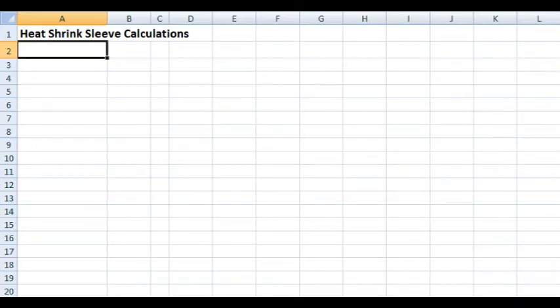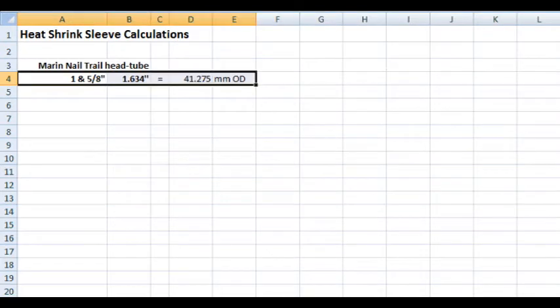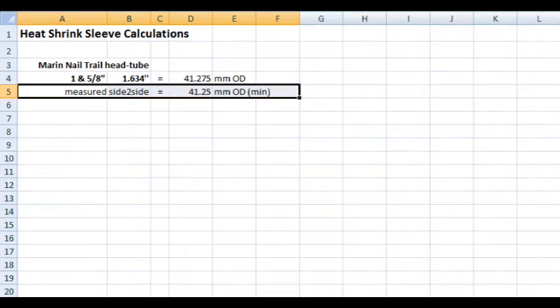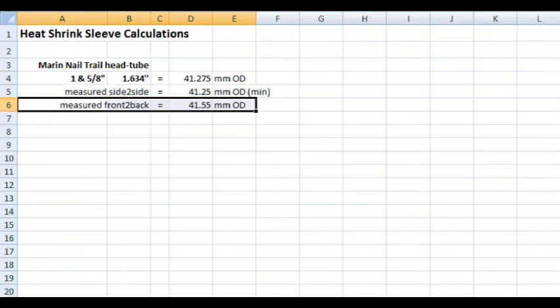First of all, we need to measure our head tube. The Marin Nail Trail head tube is made of 1 5/8 of an inch alloy. It's 41.275 millimeters OD. I measured mine. Side to side it's 41.25 at the minimum, and front to back it's 41.55, so it's within 1%, so I'm going to be able to slip a sleeve straight on this.